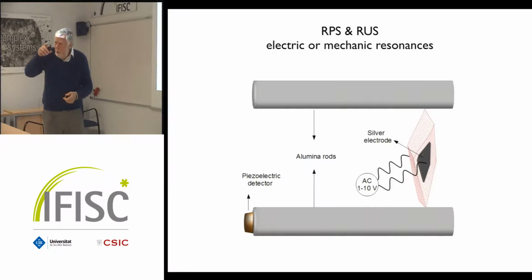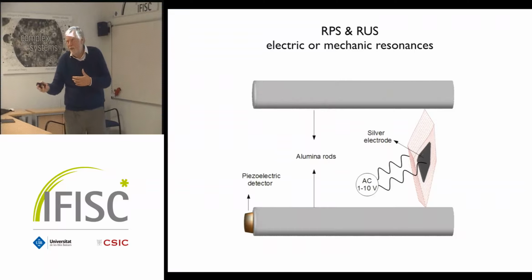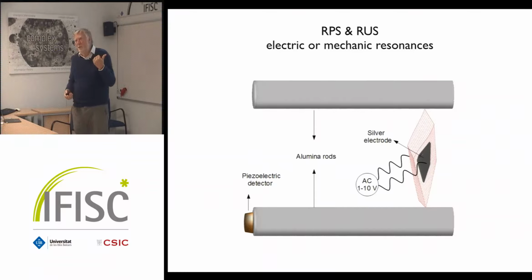But you have to go into the resonance of the swinging interfaces, and when the swinging interfaces swing, then you get a macroscopic signal, which is an acoustic signal. So you transfer from the electric signal to the acoustic signal. And that's a highly, highly sensitive way of doing that. I mean, with this one, we can be about 4 orders of magnitude more sensitive than a bulk material. And the interfaces are about 4 orders of magnitude less material. So, I mean, we are in a similar ballpark of sensitivity.